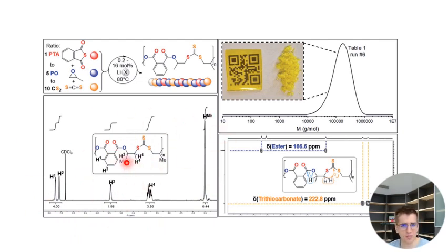And it was immediately obvious that this is not a block or a random polymer, because of the very symmetric aromatic region here, which really originates from a symmetrically substituted aromatic unit in the polymer backbone. So this could not be like a link which on one side has an ester and on the other side has a thioester, right? This would not have two signals. Yeah, it had to be symmetrically substituted. And well, so from the sheer symmetry of the spectrum, it was already clear, oh, this is not a random polymer, not even a block polymer. This is something more symmetric.